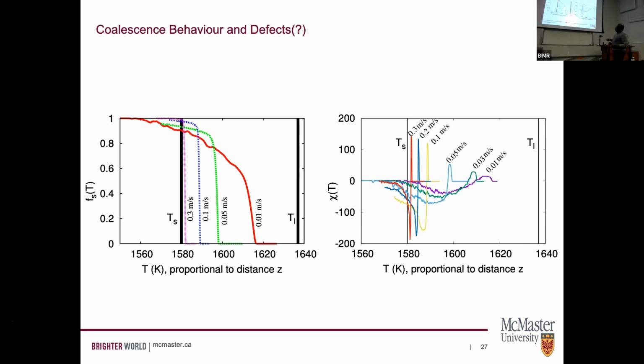The idea of, as a function of temperature, what's going on with the liquid, is we think that's where defects or secondary phases will tend to form if they're not closed. And some of these defects or secondary phases could be detrimental later on. And so if we know their distribution or where they are and the characteristics they have as a function of, say, composition, then we could feed that into other algorithms or into other theories to answer some very interesting questions as well.